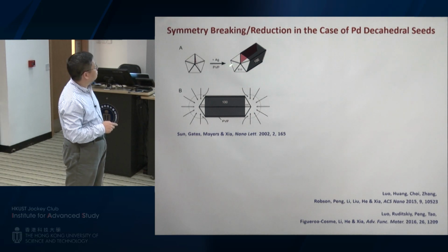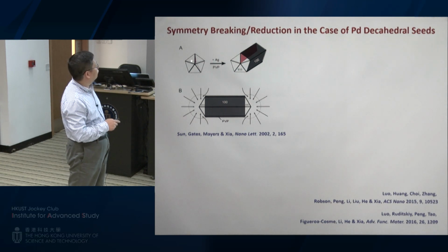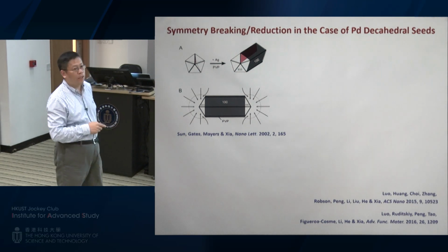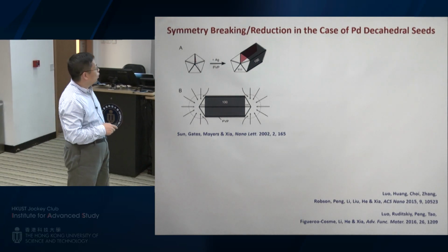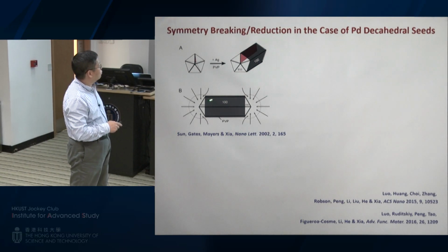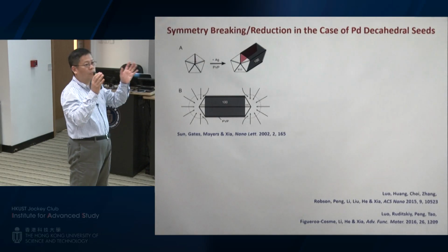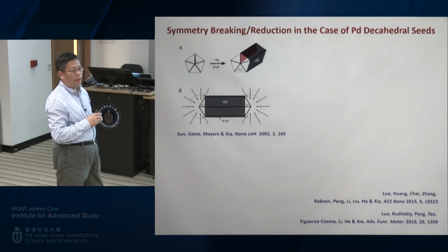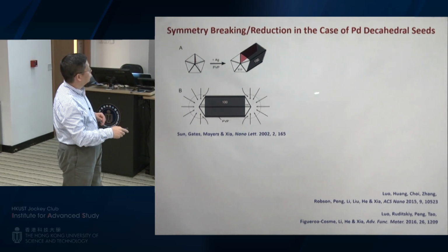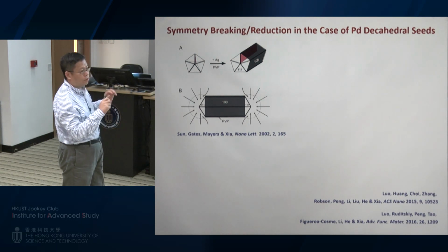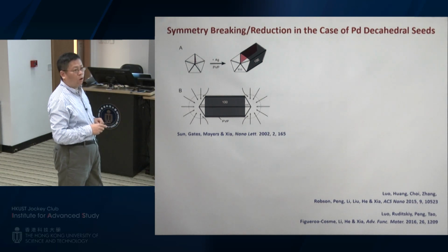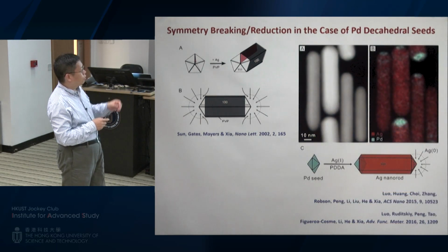And typically, like this nanowire shown over here with this particular cross-section, like a pentagonal cross-section, they are supposed to grow from the seed with the decahedron shape, okay? And in older days, we assumed this growth would be initiated from both sides of this decahedron seed, and then pushed onto both sides. So that's why the seed eventually is going to be sitting in the middle. So you're going to have symmetric growth. It turns out to be not always the case, depending on the conditions you use for the growth. The symmetry could be broken.